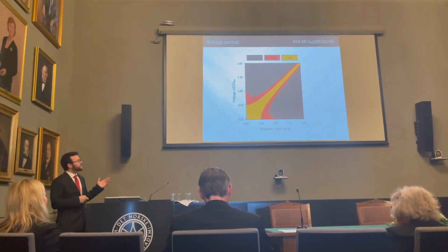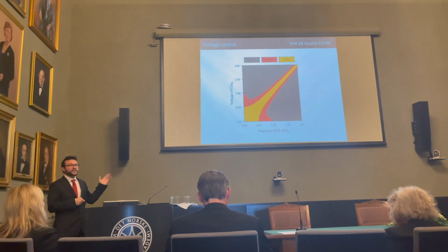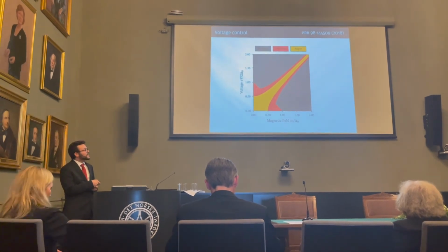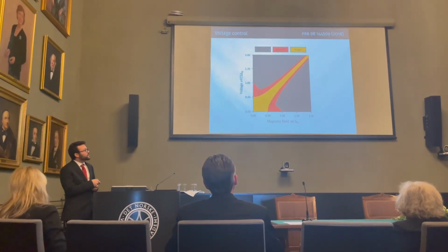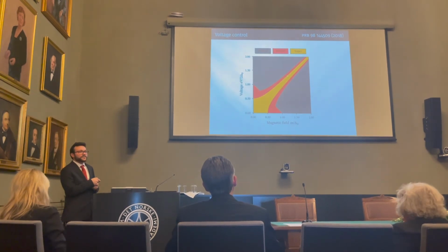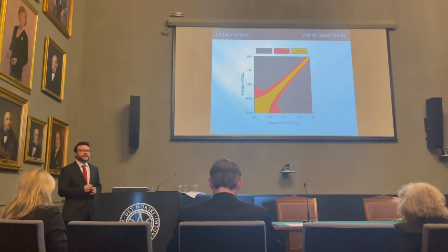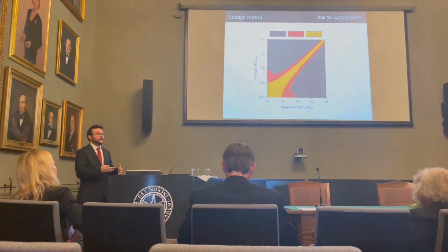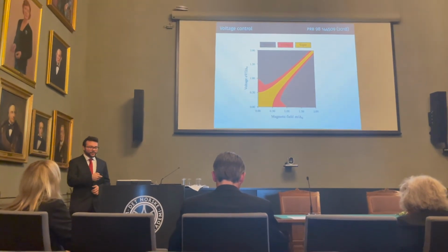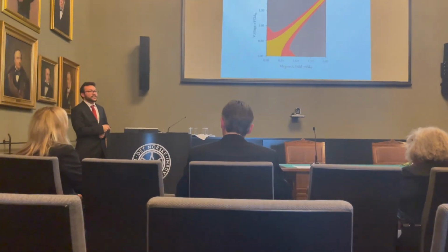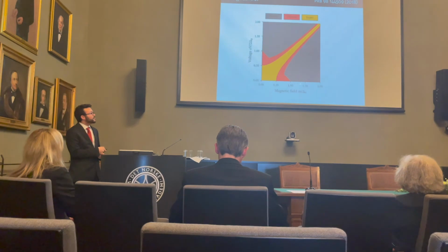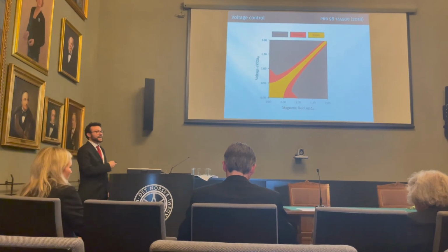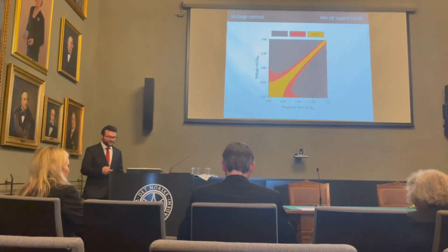The second conclusion is that this can potentially be quite useful in future electronics devices, because if you now imagine that you hold the magnetic field fixed, for example at 1 in these units, then you increase the voltage, then suddenly superconductivity appears. And superconductivity appearing would mean that suddenly you would get a very large electrical current, because you can have a resistance-less current flowing through the system. So this behavior is quite similar to a transistor, which is used in all classical computing. You can use a voltage to turn on or off a very large current, in this case a supercurrent. So this has potential applications for future superconducting computers.